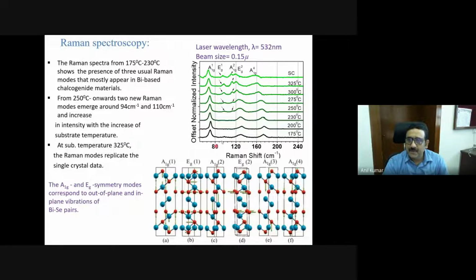See, the films grown at different temperatures. Finally, we compare with the single crystal data, and we find that the optimum growth temperature is the one that gives me exactly the same Raman spectra as my single crystal. And we get a lot of information from these Raman spectroscopy studies.